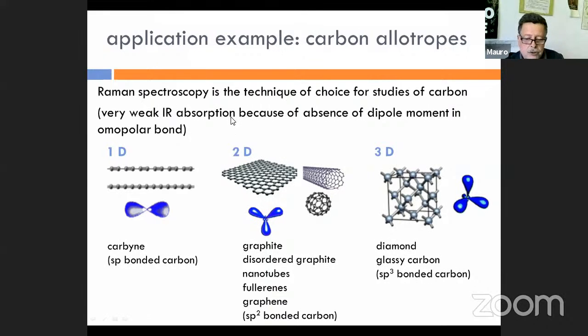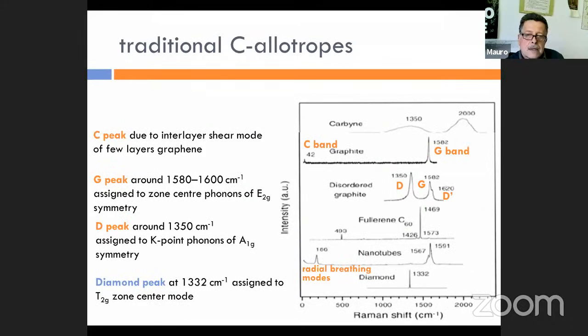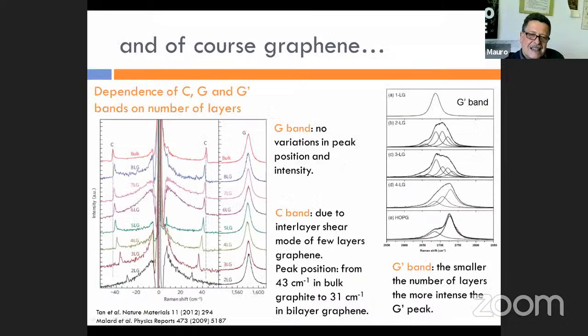And this is why Raman is the technique of choice. And here we see some examples. Each structure has well-defined Raman bands. So this demonstrates the kind of fingerprinting. If I have some carbon material, I can analyze it by Raman, and if I see sharp bands, that can be graphite or diamond, and these bands are sharp because these are usually very good quality crystals. When you have disordered graphite, the features smear and widen, and we have new bands created by the disordered bonds. And also, if somebody gives you a gift saying this is diamond, you can put it under Raman and see if it is diamond or a piece of glass.